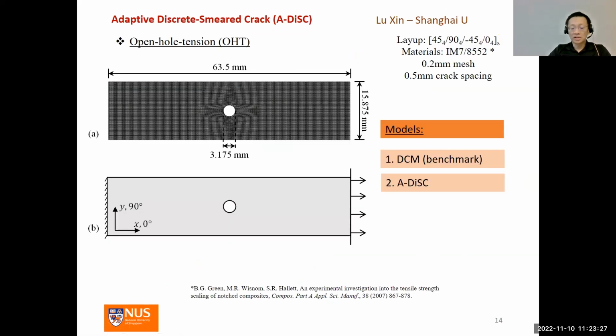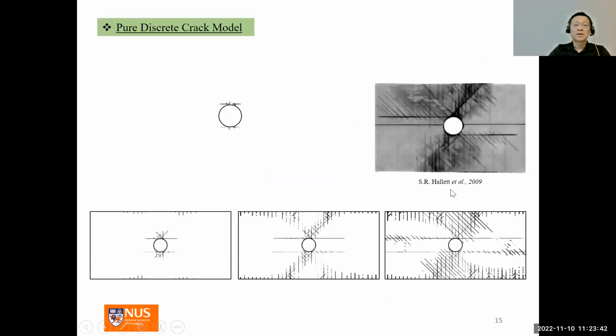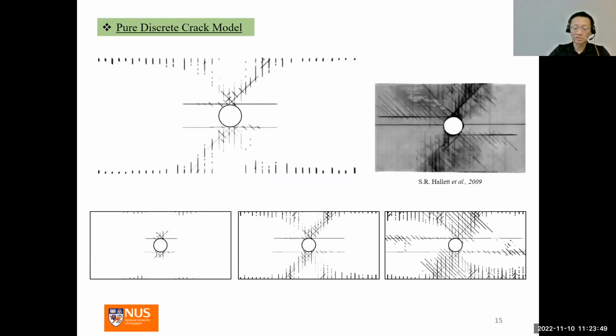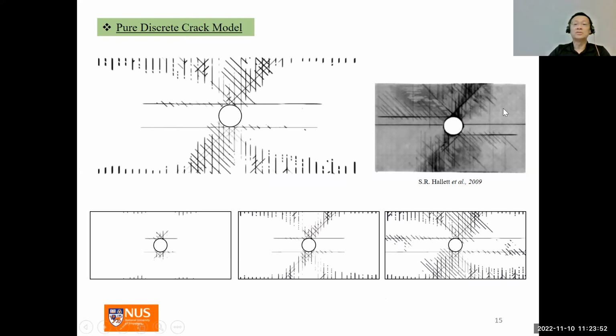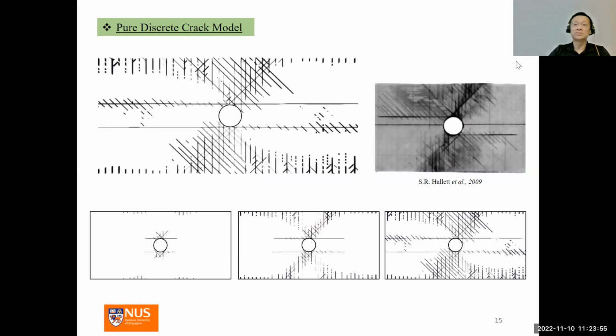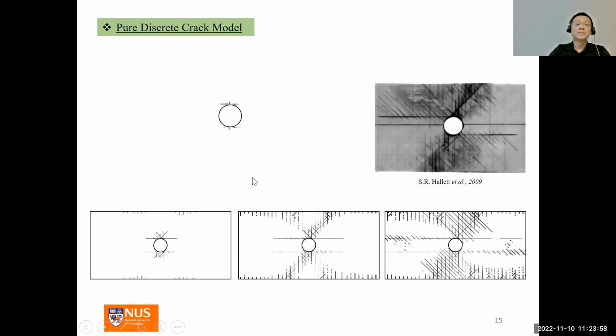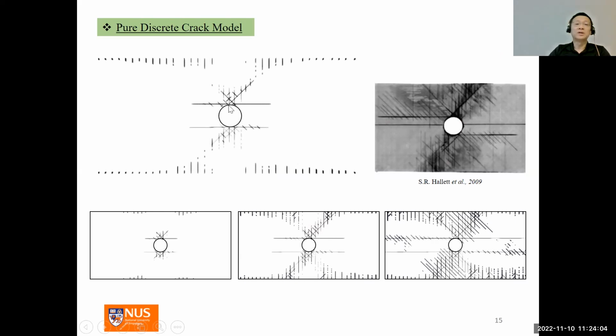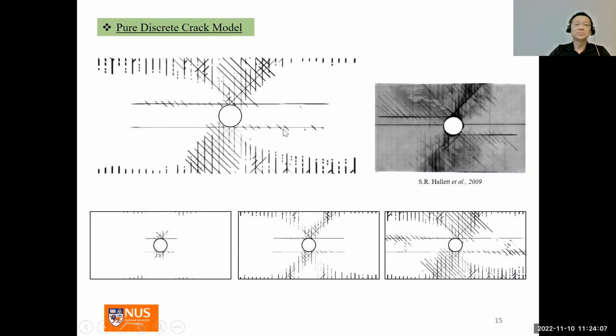So I'd like to demonstrate this approach in an OHT of a quasi-isotropic laminate, for which experimental results are well documented by a paper from Steve Hallett. Here, we show the modeling with the full 3D discrete crack model. And on the right is the picture of the experimental results from the paper. So here you can see that the elements are partitioned from the cracks. There's a longitudinal split at the 0 degree ply, like so.